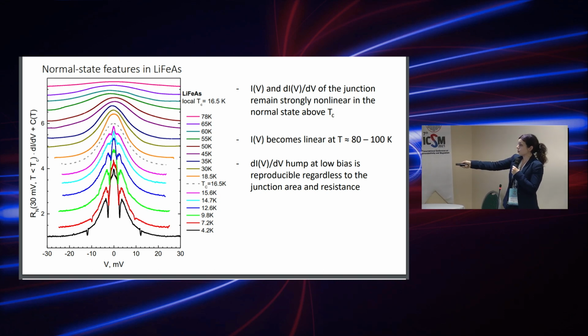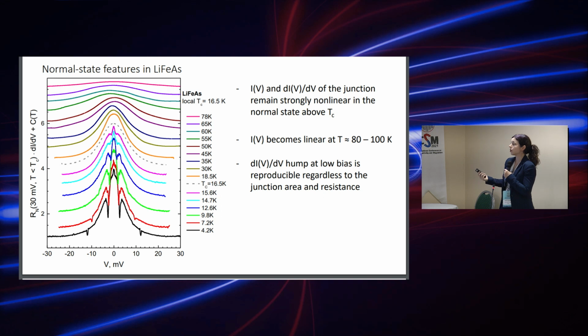At lower temperatures, below Tc, on this strongly nonlinear background, the sharp structures caused by multiple Andreev reflection transport also appear: the gap dynamic conductance dips and the Andreev-enhanced zero bias conductance peak.